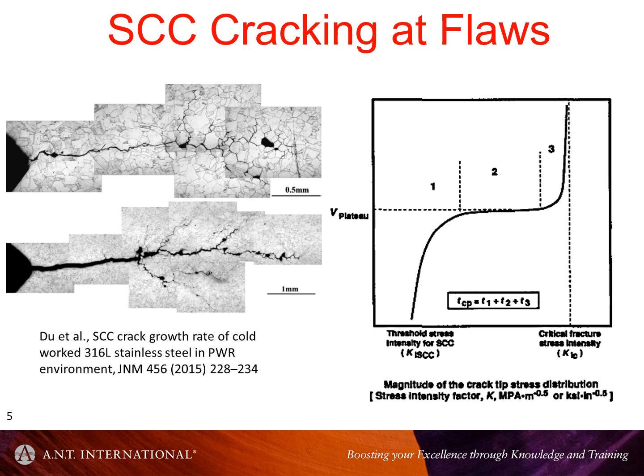It seems that stress corrosion cracking follows a somewhat similar velocity versus K_ISCC or K_IC curve, exactly the same. Below a certain stress or stress intensity, you don't get any action, but once you exceed a certain stress intensity, that's a combination of the stress and the crack dimensions, the thing can start progressing, and in a slow strain rate test, you get a crack velocity.